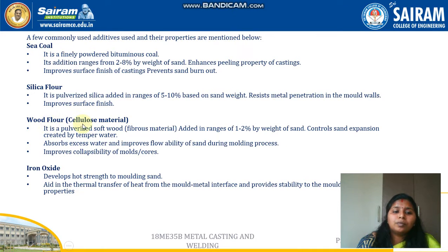Then wood flour, a cellulose material. It is pulverized softwood added in ranges of 1 to 2% by weight of sand. It controls the sand expansion created by temper water. It absorbs excess water and improves flowability of sand during the molding process. It improves collapsibility of molds and cores.